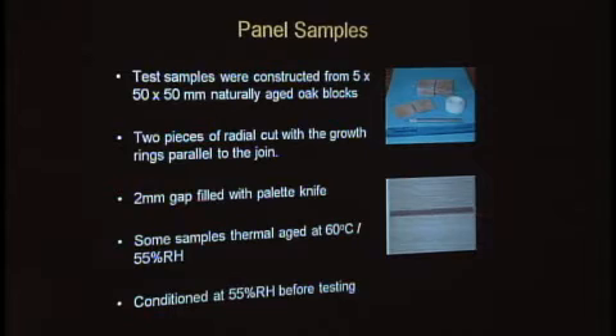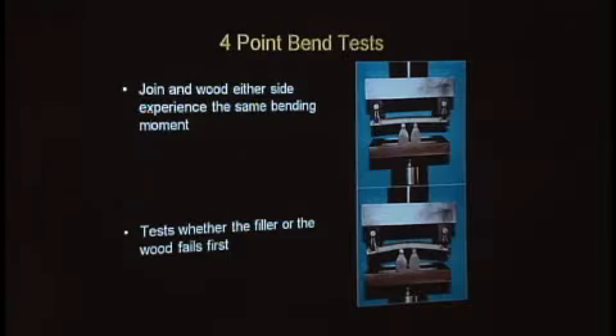Some of them were aged at 60 degrees C and 55% RH. Some were naturally aged. There's a big debate that could be had about thermally ageing above the glass transition of most of these adhesives, but I think that's really for another discussion at this point. I can show you the results of both, and you can make your own mind up about the validity of that approach. All these panels were then conditioned at 55% RH before testing.